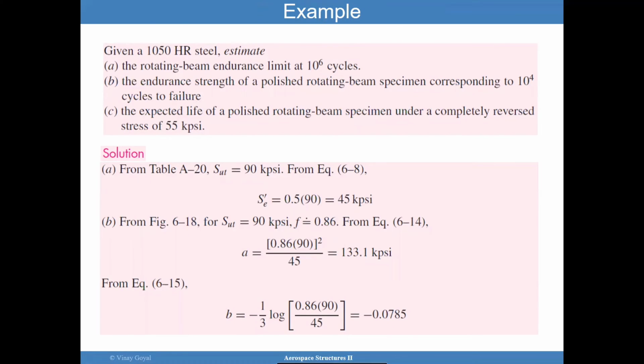And then here's an example. If you have a rotating beam with an endurance limit of 10 to the 6 cycles, the endurance strength of a polished rotating beam corresponds to 10 to the 4 cycles to failure. And then the expected life of a polished rotating beam under completely reversed stress is 55 ksi. So we want to estimate the expected life, the endurance strength, and then the rotating beam endurance limit at 10 to the 6.